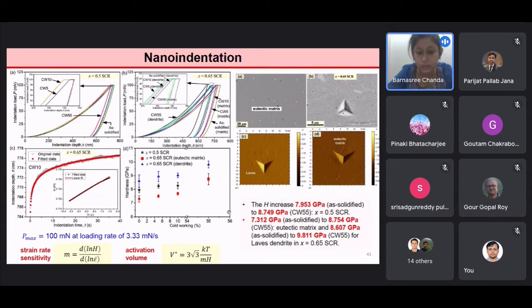The hardness and the variation of the hardness with cold working has been shown in figure D, where we see that as the cold working percentage increases, there is an increase in the hardness. Also, the hardness is highest in the case of the x equals 0.65 suction cast rod dendrites. Figure A and B shows the AFM images of the indentation matrix and the indentation impression on the eutectic matrix. C and D shows the AFM force gradient on the Laves phase on the eutectic matrix. There is no presence of any crack observed in the AFM images.